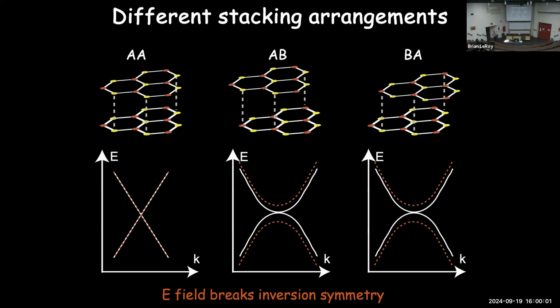Now, if I apply an electric field in the z direction perpendicular to here, that's going to break this inversion symmetry in these 2 structures, and that's going to then open a band gap in the material. So these little dashed red lines are showing what happens when I apply an electric field. Here, it does not do anything to it, and we just keep the same structure. And so basically, if I have a configuration here, I have one that stays a metal, and I have another set of stackings which become semiconducting or insulating if I'm near the center here. And so I get changes in the electronic properties with the electric field depending on the stacking configuration.